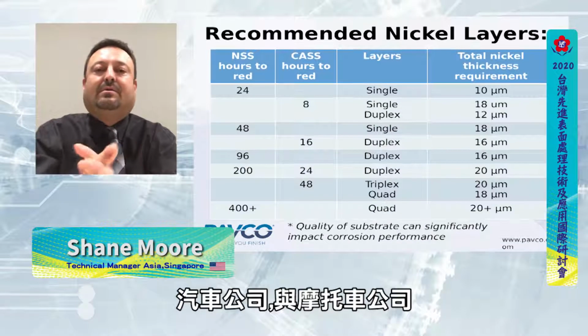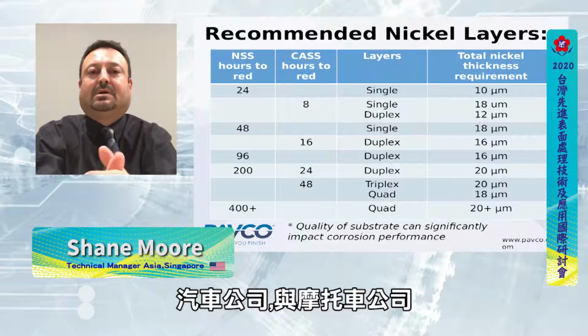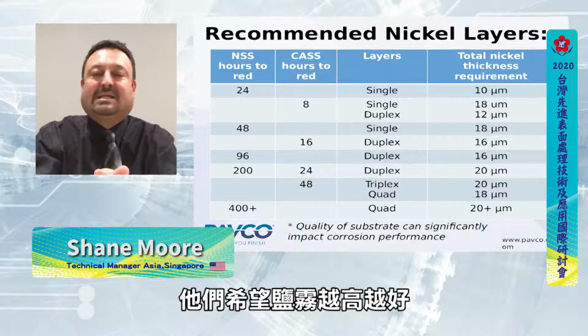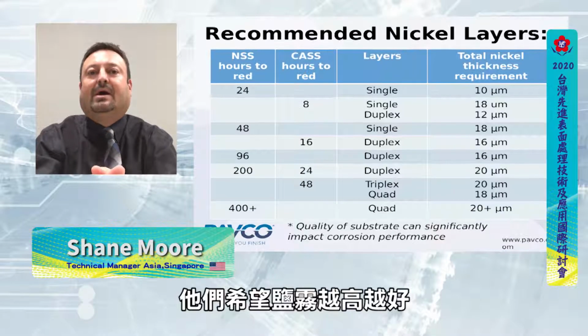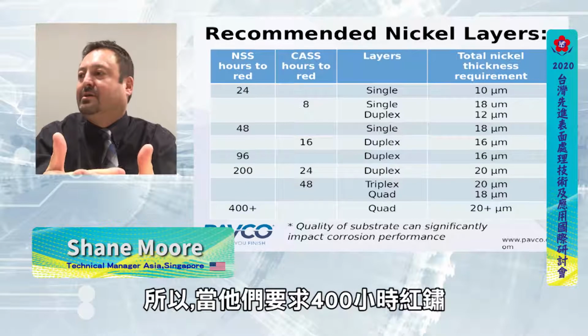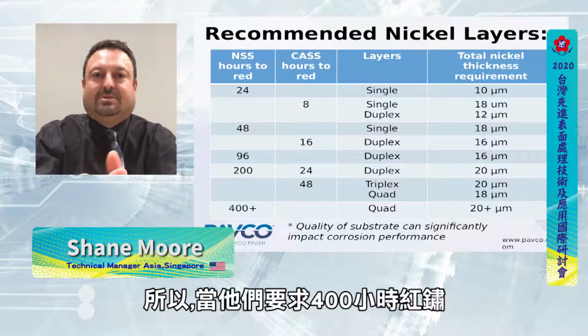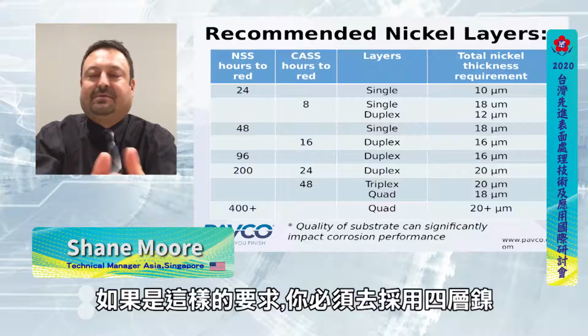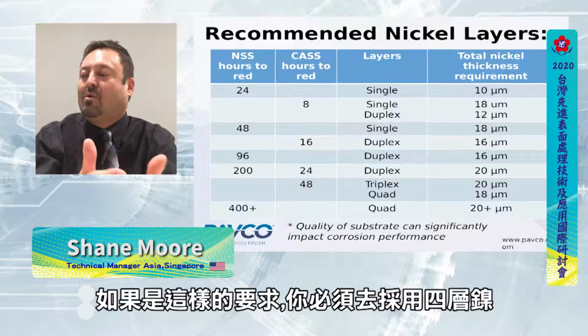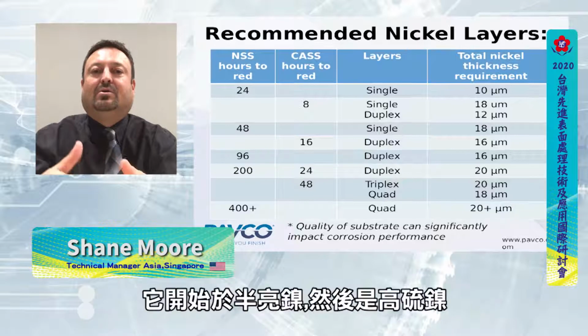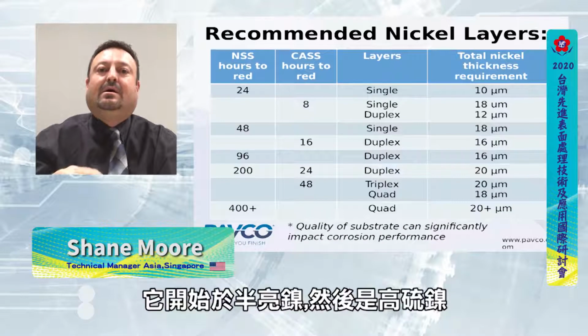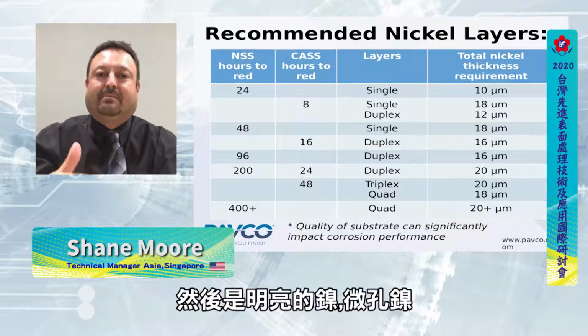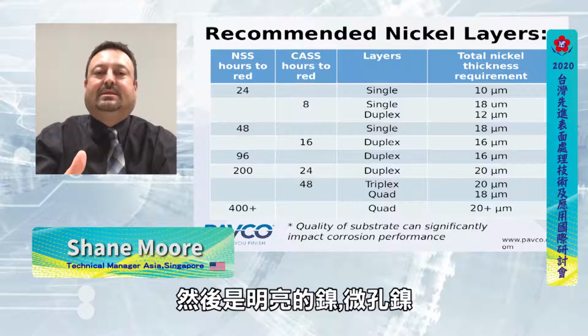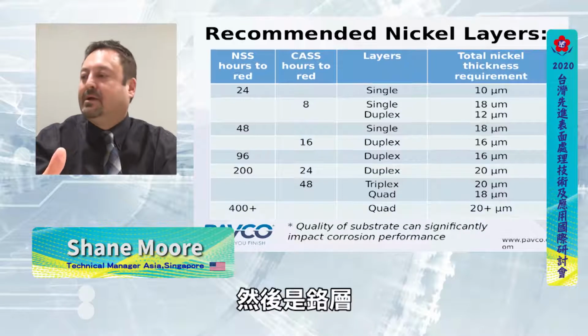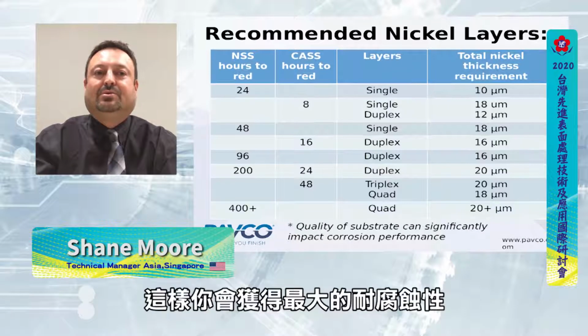Sometimes with automotive companies, with motorcycle companies, they want the maximum amount of salt spray hours. So usually that's when they're asking for 400 hours at least to red. If this is the case, then you would have to go with a quad, it's called a quad nickel stack. So it begins with a semi-bright nickel, then a high sulfur nickel, then a bright nickel, microporous nickel, and then the chromium layer. So that's going to give you your absolute maximum corrosion resistance.